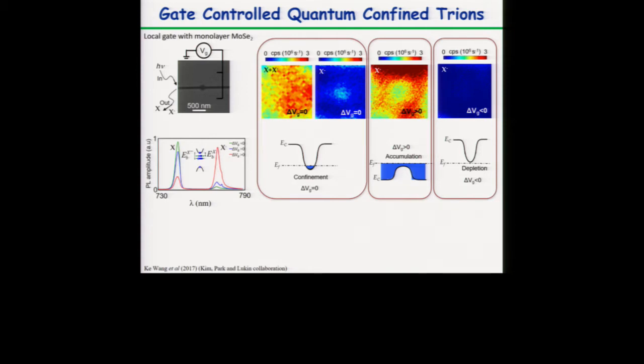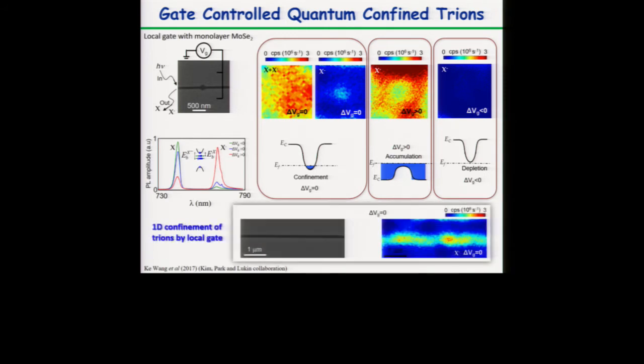So this is another example, this is a PL map as well. So we are looking at the emission from this region, which is like a quantum dot region, right? So we can control the gates to make it brighter or dimmer, depending on whether we do accumulation or depletion on these local gates. And also since they are lines, we can have a 1D confinement. So you see we are depleting this region, getting rid of trions in this region, while there are mostly trions on the ungated line in the sample, and it's mostly trion emission from that line.